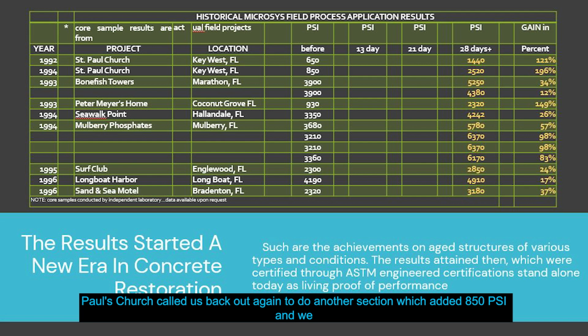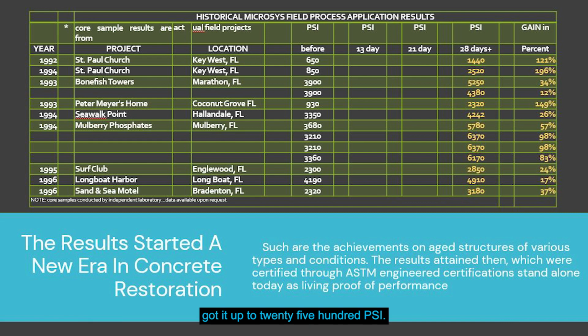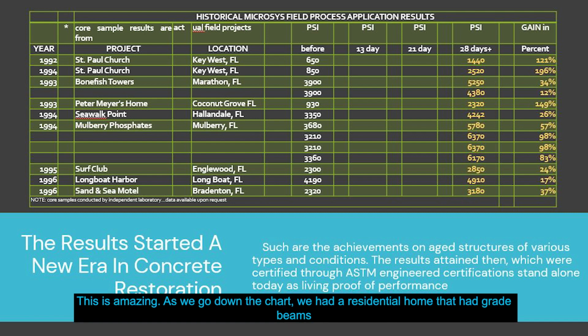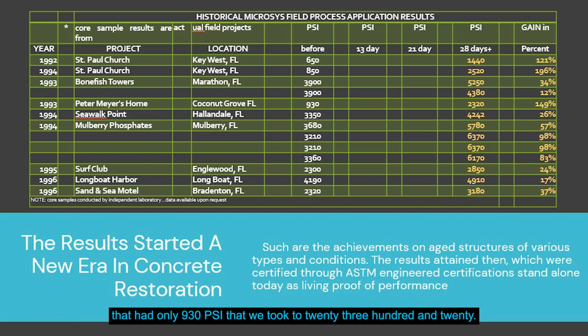Two years later, St. Paul's Church called us back out again to do another section, which had an 850 PSI, and we got it up to 2,500 PSI, a 196% increase in PSI strength. This is amazing. As we go down the chart, we had a residential home that had grade beams that had only 930 PSI that we took to 2,320, an incredible 149% increase.